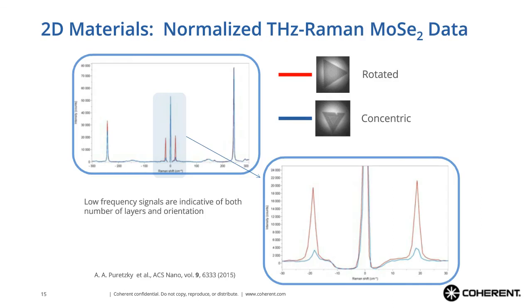One application coming from this setup is looking at 2D materials. Here we have molybdenum diselenide, where two layers of a multi-layer stack can be placed either directly concentric with the layer below or rotated by 60 degrees. When that layer rotation occurs, you can identify the difference based on the appearance of a band at about 18 wavenumbers. The signal strength of that band is massively larger for the rotated case than the concentric case, with a slight shift in band position — making this very sensitive to detecting defects in 2D materials that can be very difficult to detect any other way.